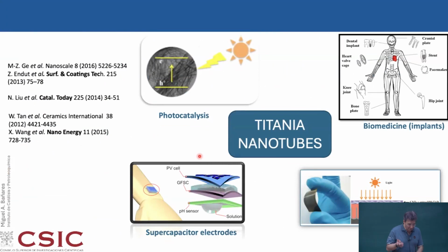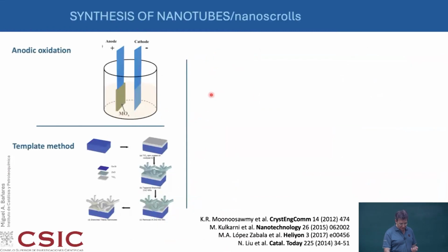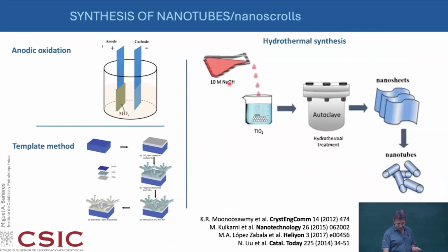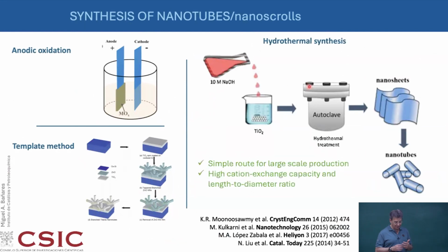Okay. So another application for microwaves is that, because of this long flow reactor, you can also make materials more efficiently than before. And titanium nanotube is a very interesting material for multiple applications. So here you have some applications in photocatalysis, of course, biomedicine, solar cells, supercapacitors. The way they typically make it, for instance, is with templating or anodic oxidation, where you develop on a surface the titanium nanotubes that they grow. Another process is the hydrothermal synthesis. In the hydrothermal synthesis, you make,